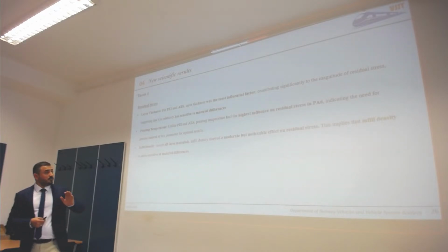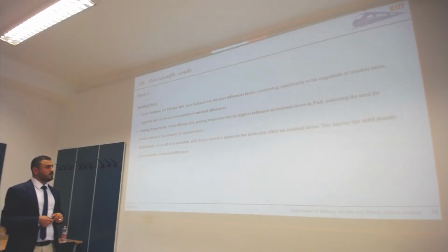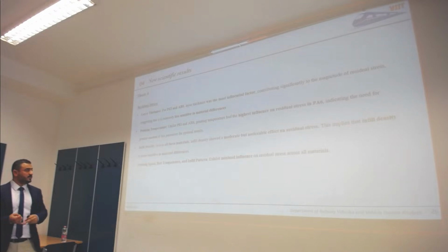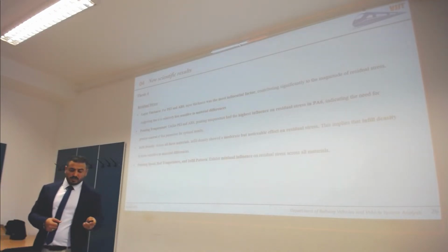Regarding the infill density, across all 3 materials, it had a noticeable effect on residual stress, and that implies that it is more sensitive to material differences. Regarding the printing speed, bed temperature, and infill pattern, there was minimal influence on the residual stress value of all the materials.